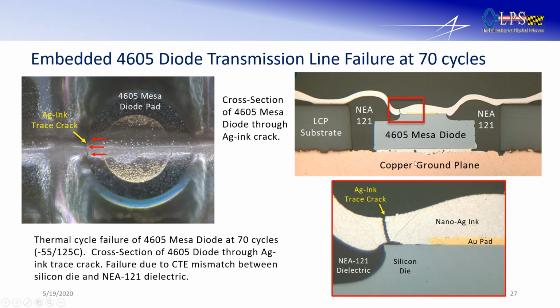And so here you can see the heavy ground plane, the die attach material, the silicon chip. In this case, it's a MESA diode. Got the bond pad, the NEA-121 encapsulation, the liquid crystal polymer substrate, and then the silver ink that's printed from the transmission line to the bond pad to the transmission line. So we had that crack right there.